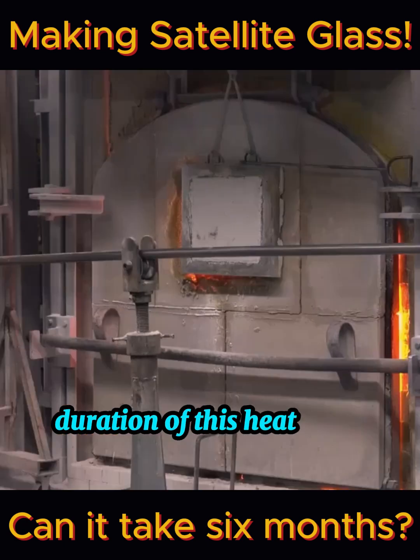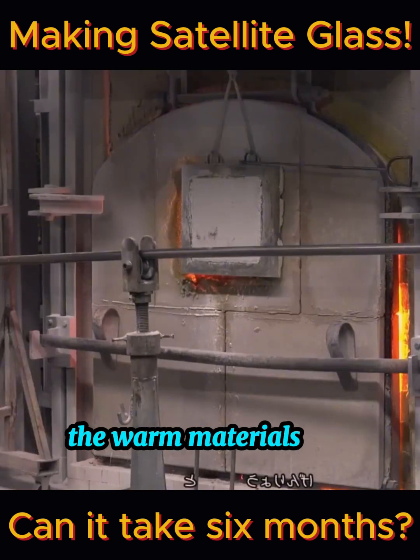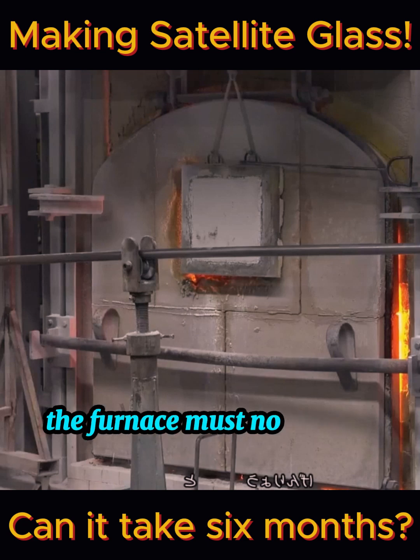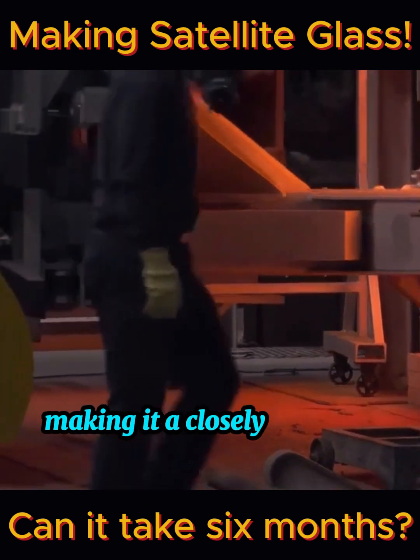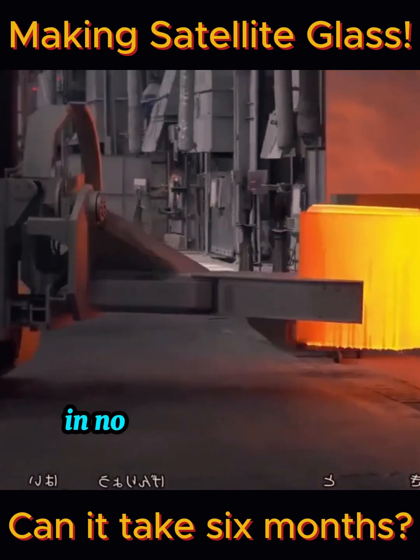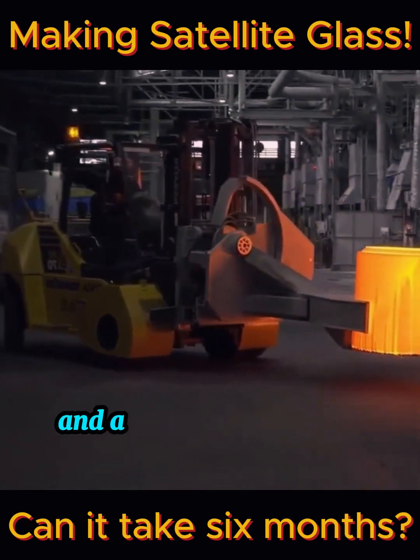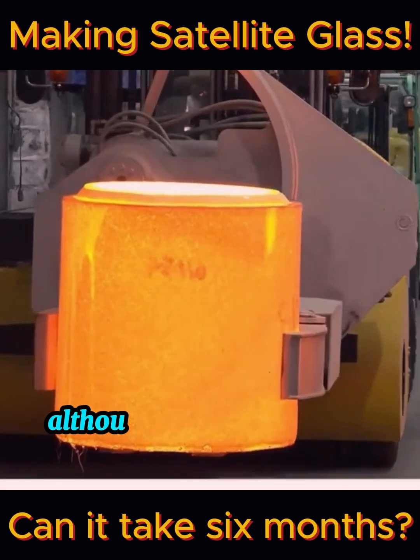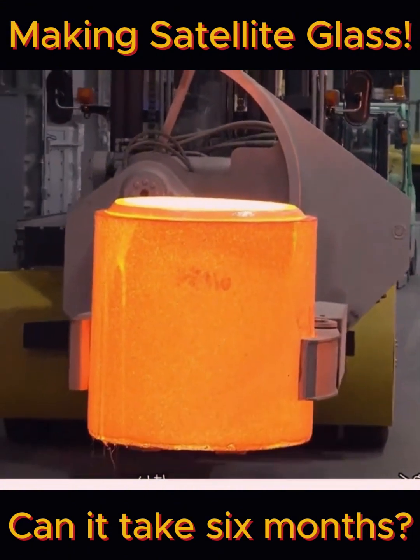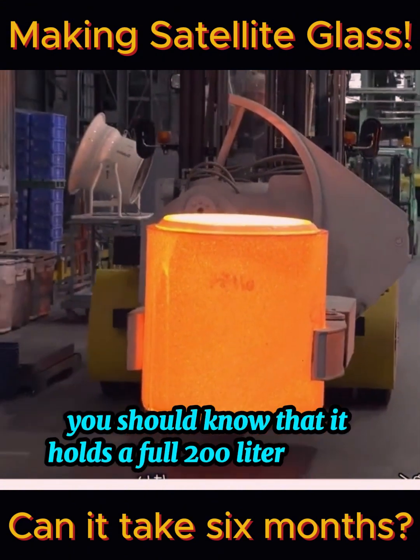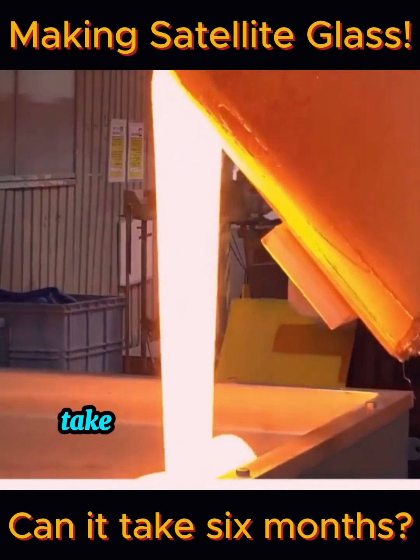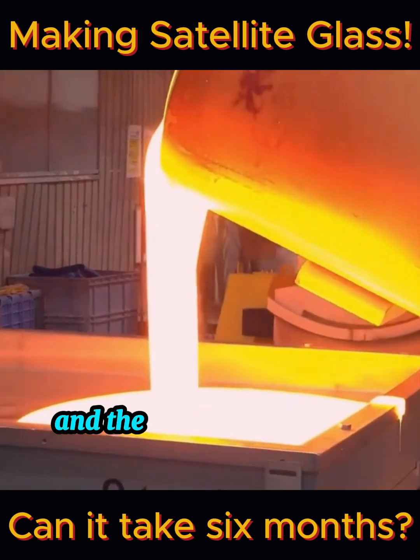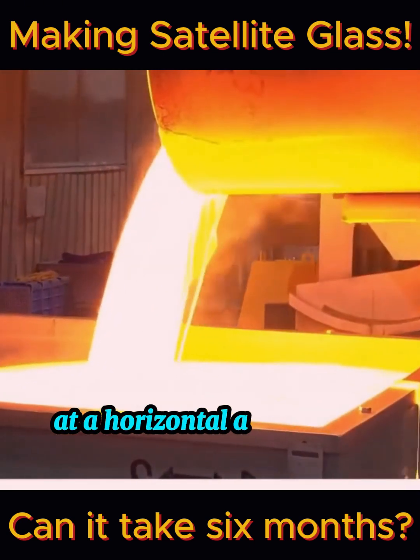The duration of this heating is closely related to the raw materials, and the temperature difference inside the furnace must not exceed 5 degrees, making it a closely guarded secret in every factory. In no time, the powder is completely melted, and a mechanical vehicle takes it out. Although this thing doesn't look very big in the video, you should know that it holds a full 200 liters inside. The melted liquid takes a long time to pour out completely, and then it has to be filled into every position at a horizontal angle.